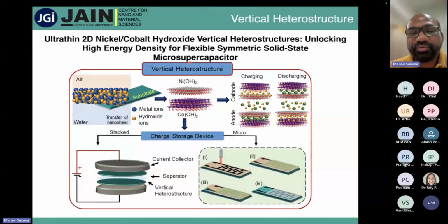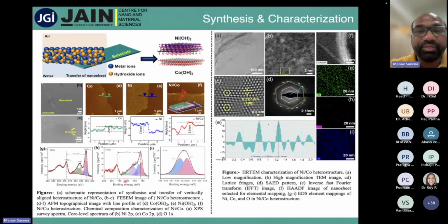In another set, we have made a nickel hydroxide film. We scooped the nickel hydroxide film on the substrate, we dried it, and then we transferred it on the cobalt hydroxide. So we make two combinations: one where cobalt hydroxide is on the substrate and nickel hydroxide on top, and another where nickel hydroxide is on the substrate and cobalt hydroxide on the top. And we use this in a micro supercapacitor device as well as a complete device.